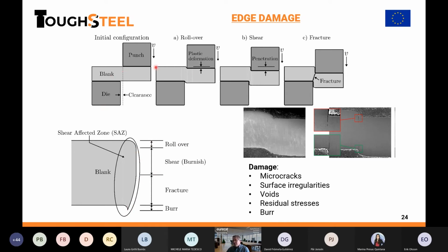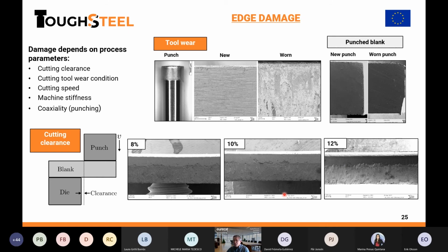If we look step by step, this is a punching or trimming process. This is a point where the cracks appear and grow through the surface. This is an image from these areas here. After some displacement of the punch, the deformation is high enough and the cracks appear and grow. So at the end, in these surfaces, we have cracks, irregularities, voids, residual stresses, everything that can be related to damage.